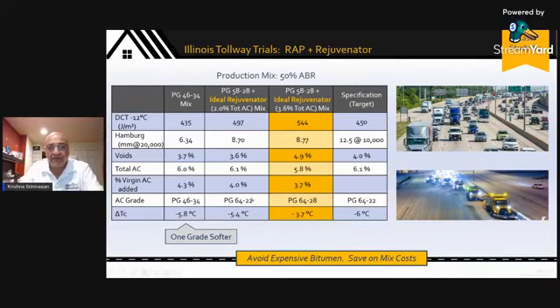They were so happy with the performance. They wanted to see what would happen if we increased slightly the rejuvenator content from 2% to 3.6% of the total liquid. And they wanted to see if the DCT number and the delta TC number were improved, because they wanted to be able to increase their specification so that it becomes more stringent.